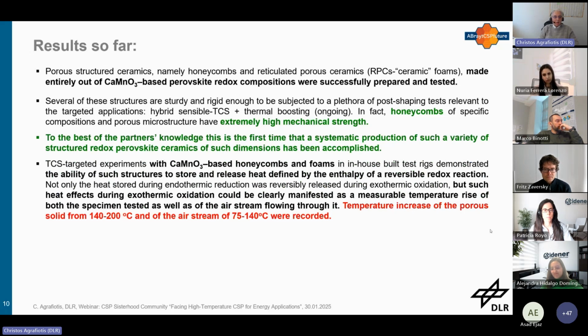So the idea is that when you pass a cold air stream through a reduced structure of this kind, the air should become hotter. Experiments in the test rigs that I showed before have indeed shown that after we reduce the material, if we pass cold air through these honeycombs, the solid itself can become hotter by 200 degrees due to the exothermic reaction, whereas the air stream that comes out of it becomes hotter, from 75 to 140 degrees, which is very good.